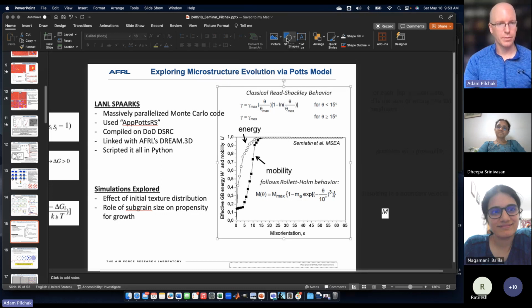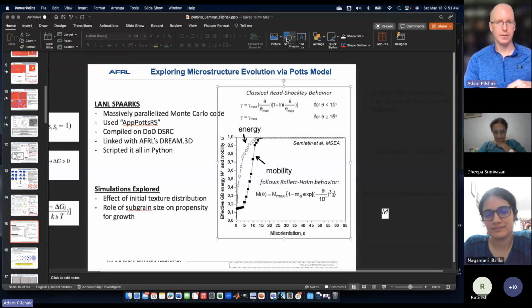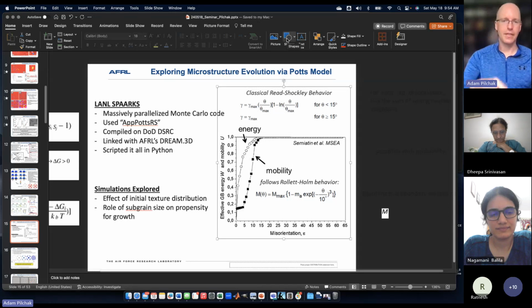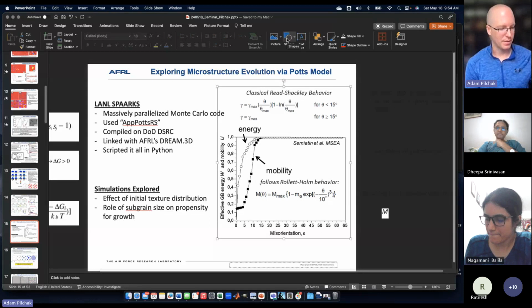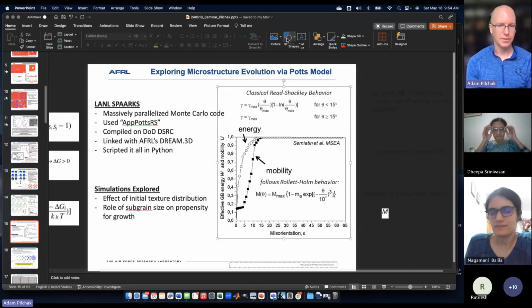Tony Rollett has a really good paper on this. They go through it for, I think, aluminum thin foil, but the hard part is you need to have grain boundaries that are basically perpendicular to the surface of your sample, because the way you derive these energies and mobilities is you look at the correlation between grain to grain misorientation, grain boundary curvature right near triple points, and then the dihedral angles between grain boundaries. And from those measurements, I don't think he developed this technique, but he's the paper I'm familiar with, they've shown the way to reduce that to grain boundary energy and mobility as a function of misorientation.